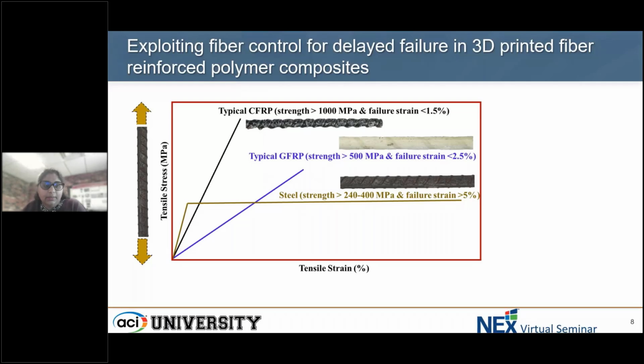I can turn on a laser pointer. If you see this linear elastic stress strain behavior compared to steel, which demonstrates this nice ductile behavior, with failure strains above 5%, that helps avoid brittle and abrupt structural failures. The brittle nature of FRP has been looked at for several decades, but has not necessarily achieved a tangible solution that could potentially solve this issue of ductility.